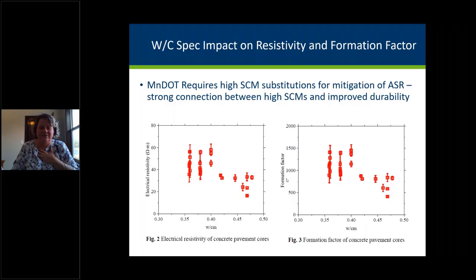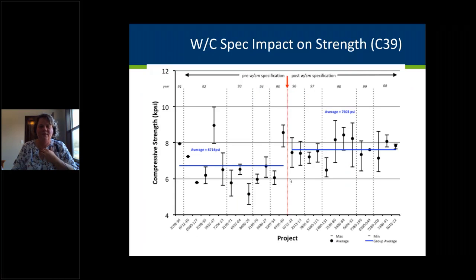Resistivity and formation factor, Jason Weiss looked at our data also, and he found similar information, that the lower water cement ratios increase your resistivity and also increase your formation factor versus the higher water cement ratios. And then strength, once again, pre-water cement average 6716, post-water cement average 7603. Keeping in mind these are 20-year-old pavements at the time.